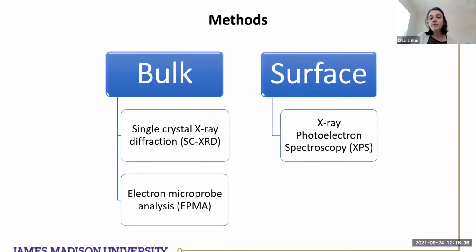The techniques that I used were different for the bulk and the surface. For the bulk, I use single crystal X-ray diffraction. So I use a little fragment, and when I say little, it is like 0.1 millimeter in diameter, of a mica. And I studied the structure of this mica. And then the electron microprobe analysis is for the chemical analysis. So how much of these cations I have in the structure, and if there's any substitution, what kind of substitution. So the electron microprobe gives me the information of the chemistry, and the single crystal diffraction, the information of the structure. And then I put together this information to define the structural formula of the mineral.